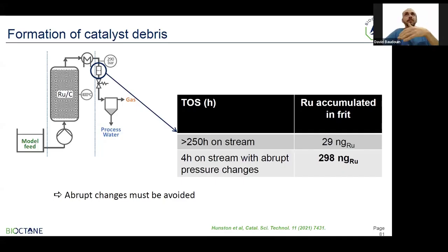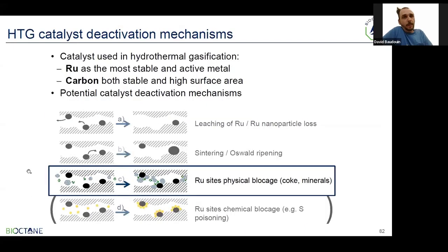during a process for different reasons, from leaking or from uncontrolled sampling, for instance, we observed that there was a very large amount of ruthenium just in the frit, and also much higher amounts in the processed water obtained downstream. Next slide, please. So that was a conclusion. We identified conditions that should not be applied. Process conditions should not be reached, in order to avoid damage to the catalyst beds, particularly on large scale. Okay, next slide, please.